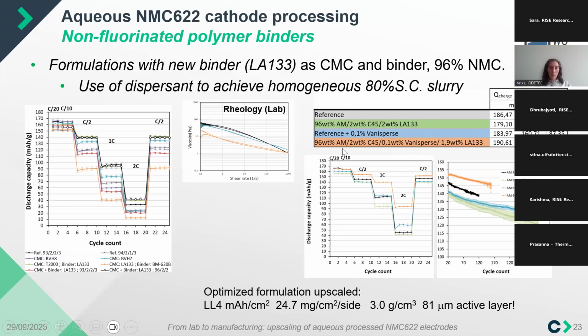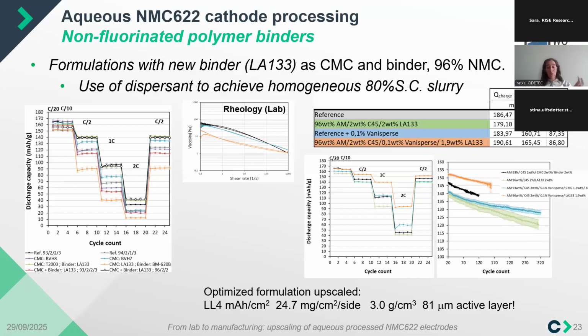And with this formulation, it has also been possible to reduce the percentage of the binder to 2%, which is already quite low, with good electrochemical performance, good rheology to go to upscaling and coating, and also to reach more than the standard baseline in terms of electrode loading in milliampere-hour per square centimeter. For instance, in this case, nearly 25 milligrams per square centimeter per side—thicker electrodes, but still maintaining the adhesion and mechanical stability.